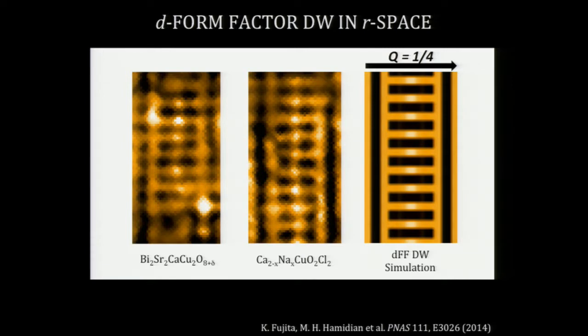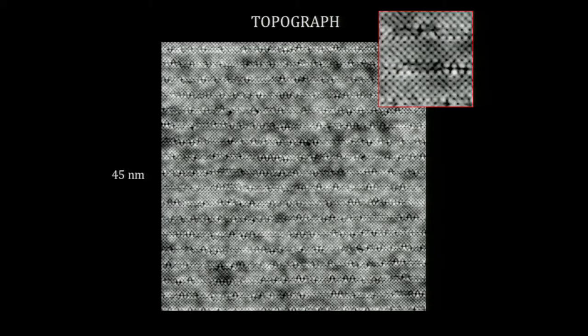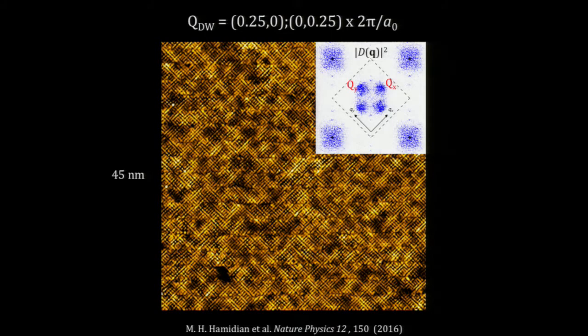We don't understand how this arises. There are theories for it, but it doesn't seem to all mesh with everything else that we know. You have to really force in the models to get a D-symmetry density wave to come out. This is just a topograph of a large field of view with these ladder patterns in them. Through some special analysis techniques, we can find that actually the periodicity is about 4 unit cells, as I've shown here. And this is going to become important later because I want to relate this structure to the paired density wave structure that I'll show you later.